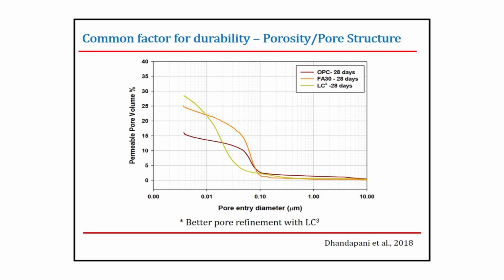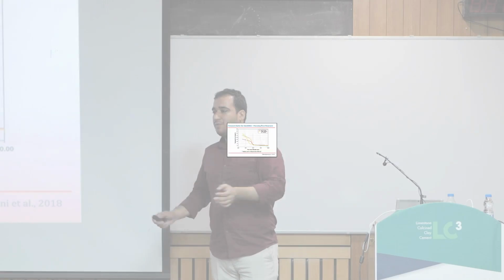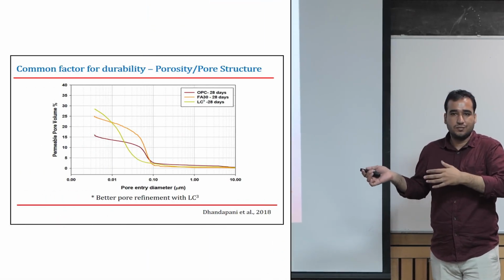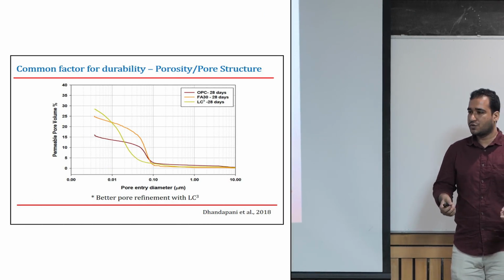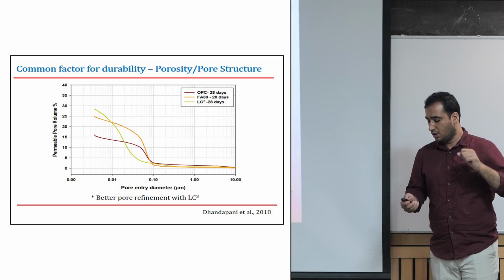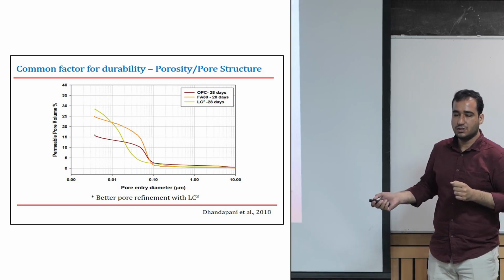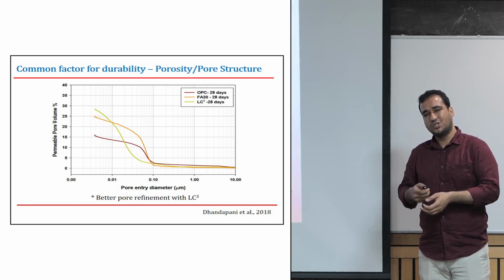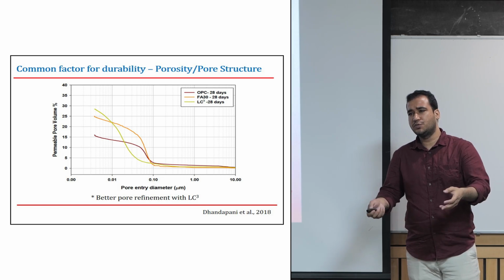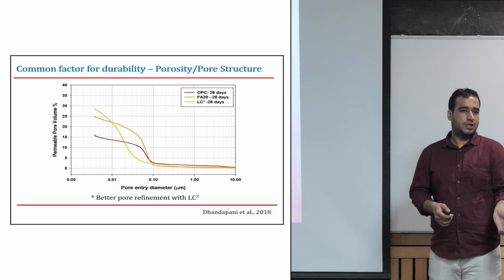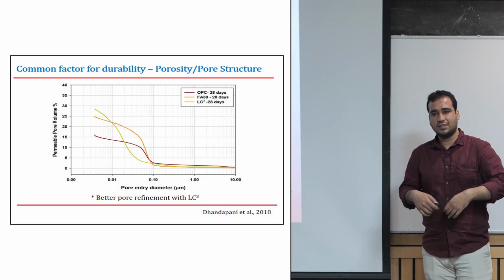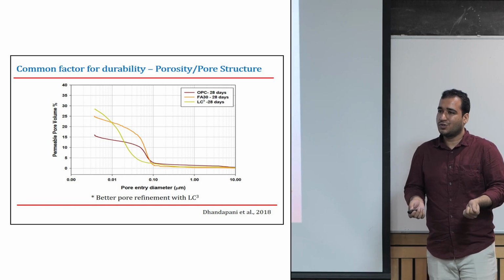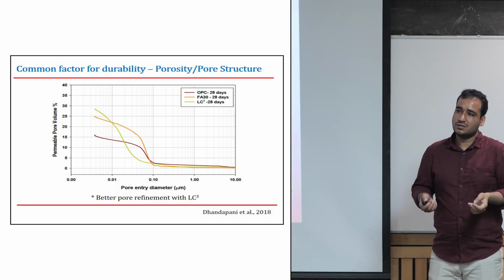So before I get into each, since we are at a workshop on LC3, and I told you pore size and pore distribution is the one thing that influences everything, I want to let you know about the pore size distribution and porosity of an LC3 system. If you assess LC3 system porosity by water absorption or even MIP, and you just look at the final value, you would generally see that you are getting a high value compared to OPC. That's the case with most of the blended systems. If you do a MIP or water absorption, you are probably going to have a higher porosity than OPC. But is it porosity alone that decides the transport or the damage or the ingress of the species?